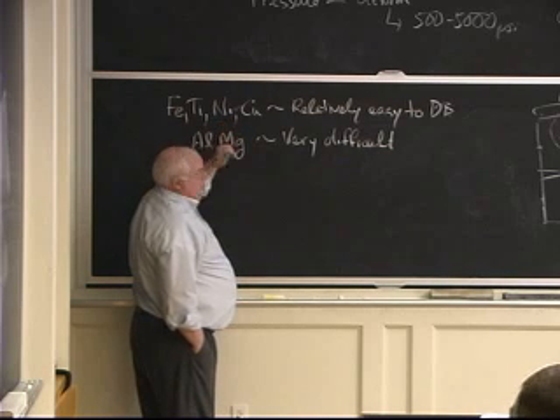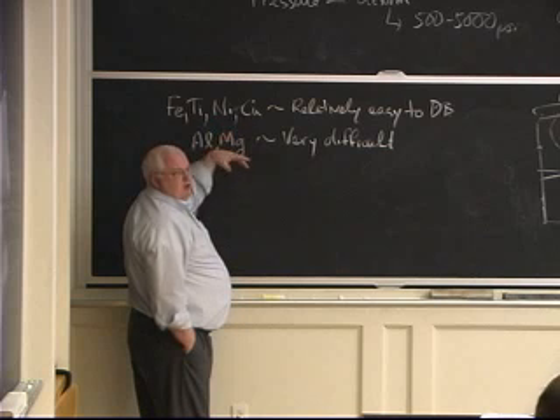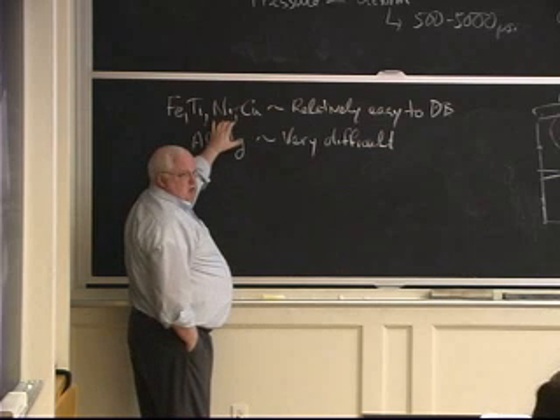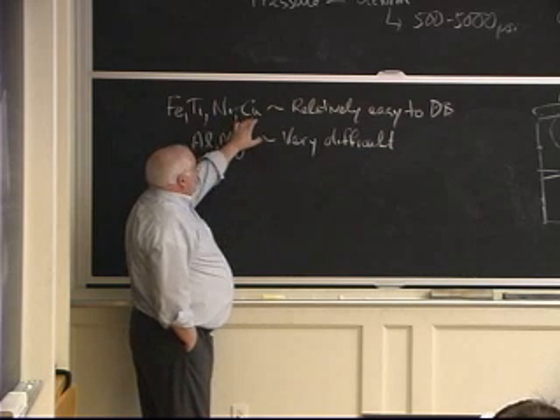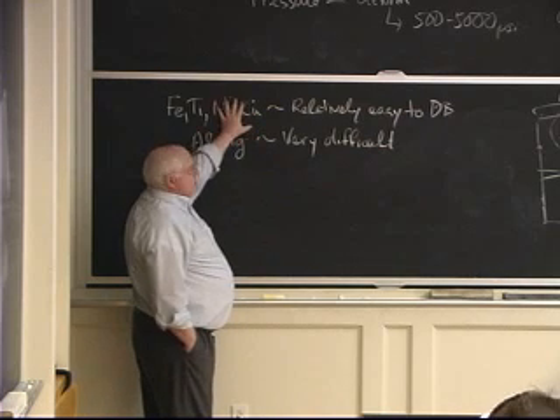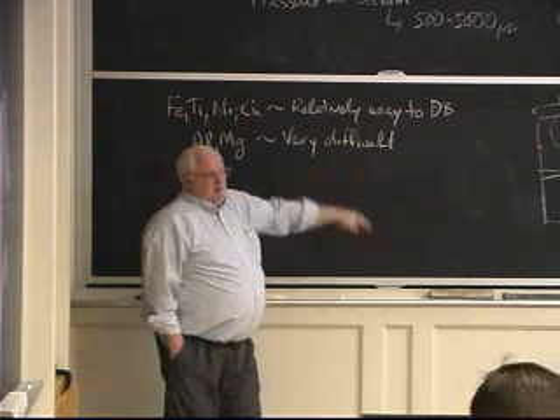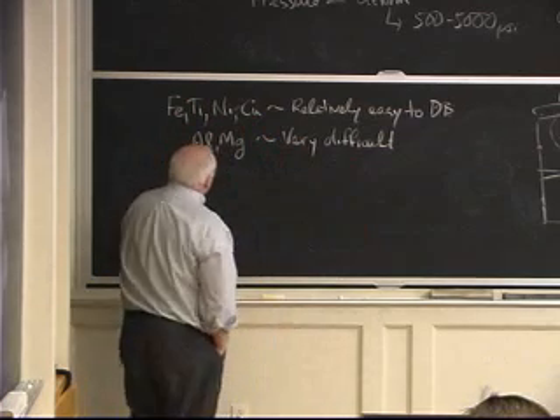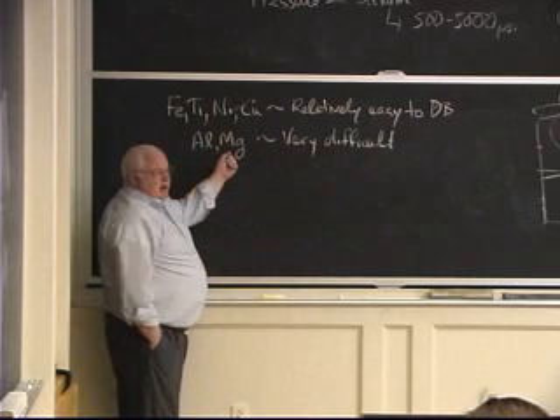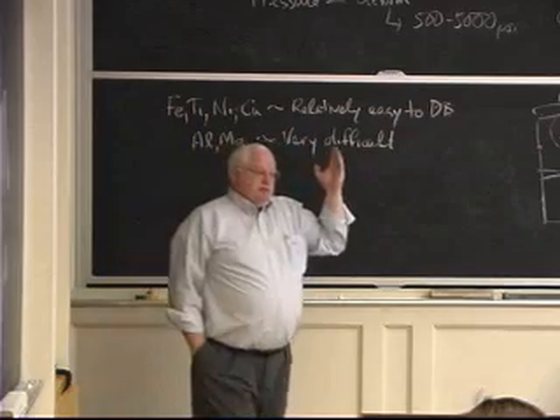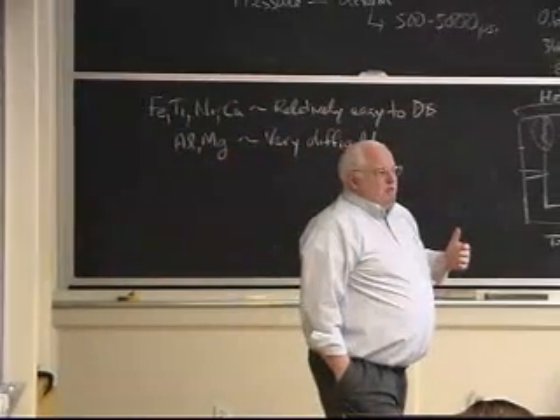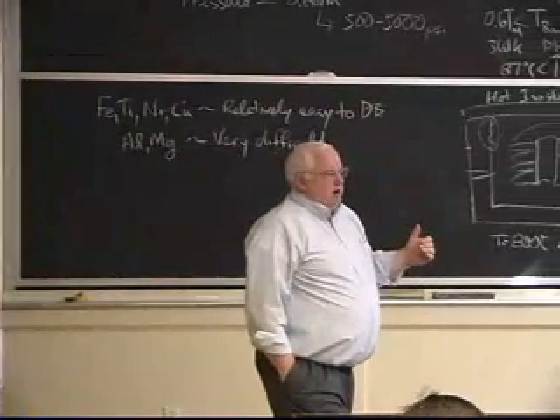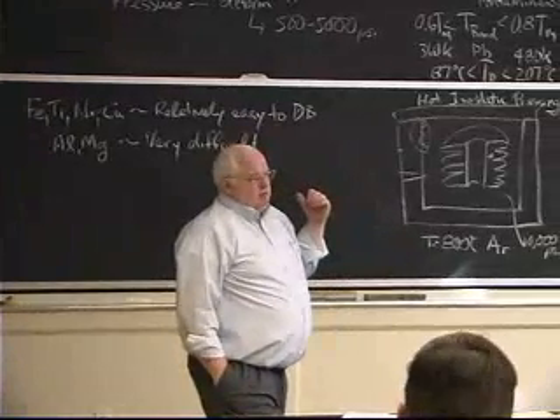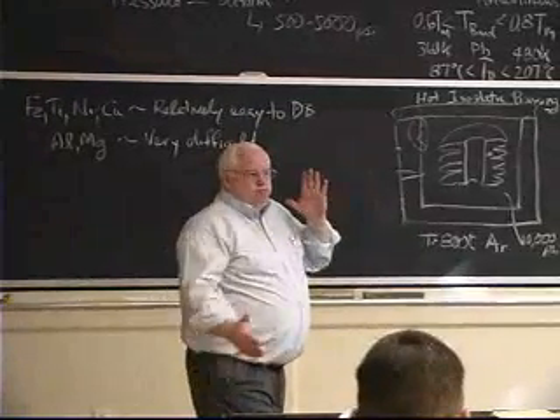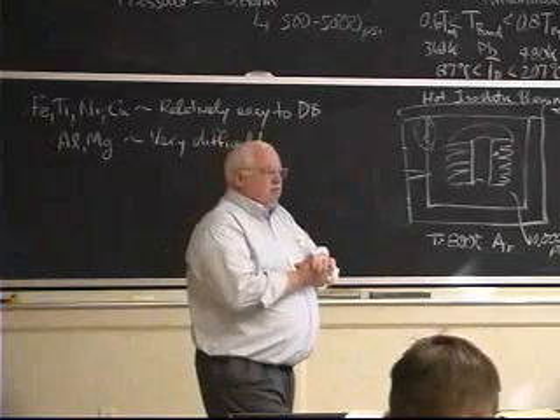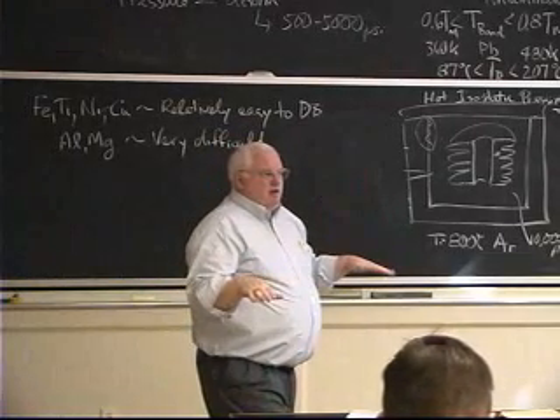So I've got to have something else in that nickel alloy, and many of the things that are in those nickel alloys will take up the carbon, but pure nickel doesn't like carbon. Copper doesn't like carbon, so that's why these two are a little bit harder than those two. But generally, you can diffusion bond all four of those. The problem here: aluminum and magnesium both melt around 650, 660 centigrade. Their oxides melt at 2,000 to 2,800 degrees centigrade, and they don't dissolve oxygen in the middle. So you can push these two pieces of aluminum together till you're blue in the face, and you'll still have an aluminum oxide layer.